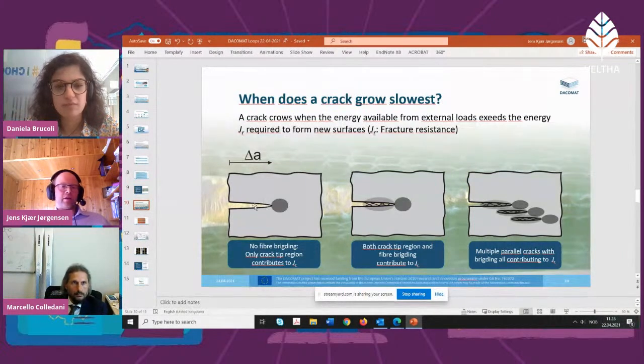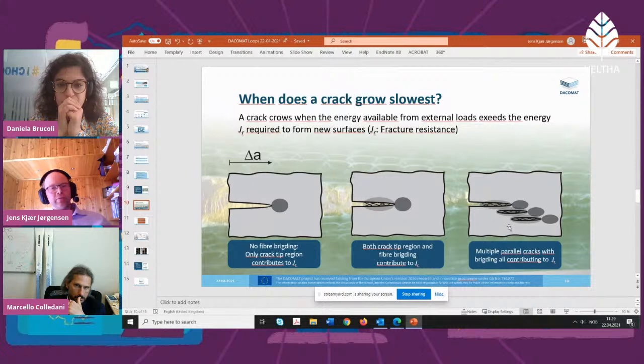If you have a crack in a laminated composite without any fiber bridging, the energy that will be dissipated for the crack to grow is the deformation of material in front of the crack tip. If you have fiber bridging, you will in addition need to dissipate energy by cracking, deforming, destroying material, and wrapping out the fibers in a longer zone behind the crack tip. So you have two areas where energy is dissipated that you need to overcome. If you then in addition have multiple cracks, you can add those together. So two cracks growing closely in parallel will require more energy than one, and by that you have a higher fracture resistance.